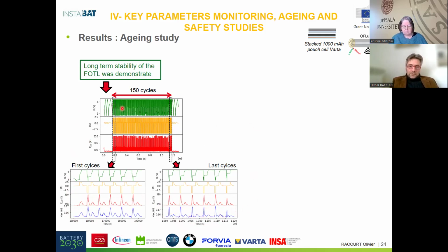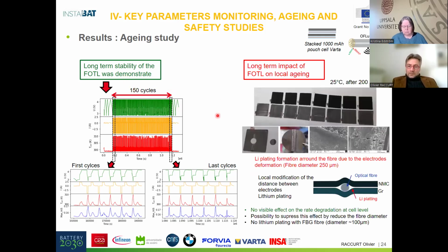And it's a proof that the sensor is stable over all the tests. And if you open the cell, now I show you one of the results of the project: the impact of the sensor on the degradation of the cell itself. We show that there is no difference in the global performances of the cell between the instrumented cell and the non-instrumented cell, but when we take a look in detail, we can show there is an impact locally in the electrode.